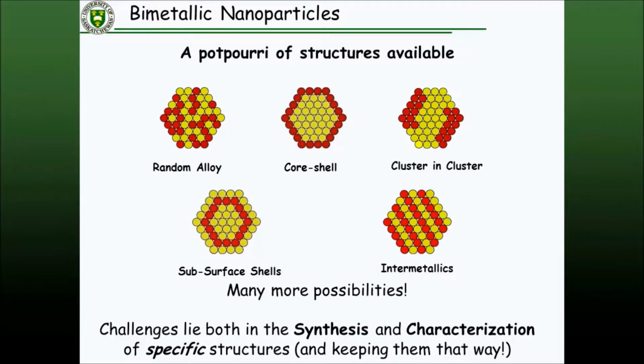The issue when you start getting to bimetallics is that now you've got two metals in the same particle, so you've got a huge number of possible structures. There are the alloy and core-shell types, what I call cluster-on-cluster systems, which have particles growing on other particles, and subsurface shells, which have been shown in a lot of single crystal studies to be very important. And then there are intermetallic compounds that can be formed. So it's not only about trying to synthesize these things, but actually characterizing specific structures and trying to keep them that way during catalysis. We got into this field when we first started in Saskatchewan.